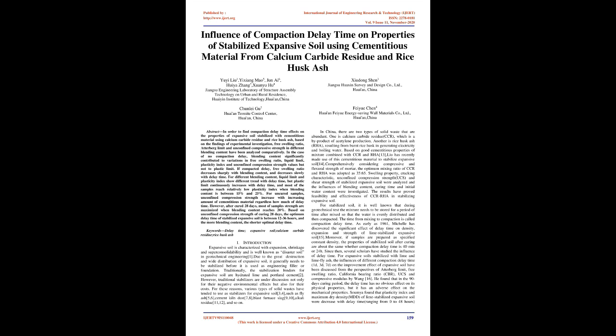In the case of no compaction delay, blending content significantly contributed to variations in free swelling ratio, liquid limit, plasticity index, and unconfined compression strength values, but not to plastic limit. If compaction is delayed, free swelling ratio decreases sharply with blending content, and decreases slowly with delay time. For different blending content, liquid limit and plasticity index show different trends with delay time, but plastic limit continuously increases